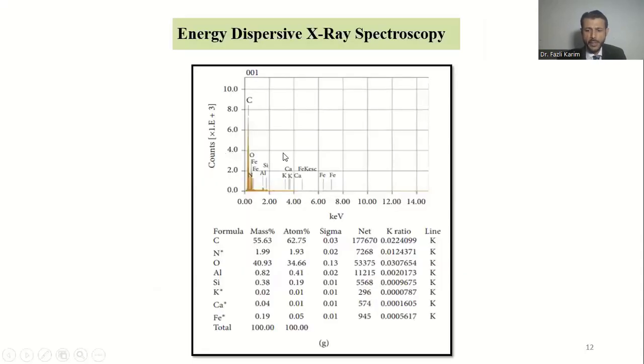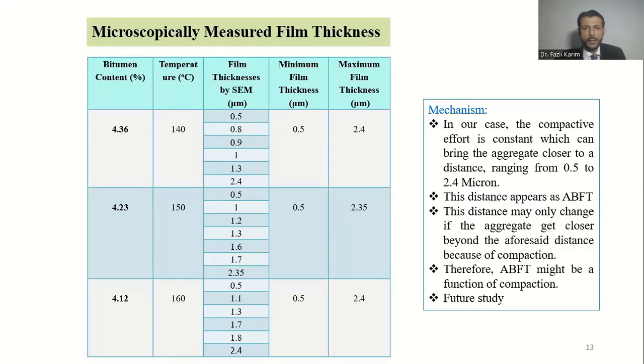So again, EDX was basically conducted to show the existence of pure binder film. Similarly, all the film thicknesses concluded from image analysis were tabulated in this table. This is basically different binder content, optimum binder content at various temperature for 3-mix design, and these are film thicknesses. And almost it exists in the same range. At 140 degrees, 0.5 to 2.4, here again 150, 0.5 to 2.35, and again 0.5 to 2.4.